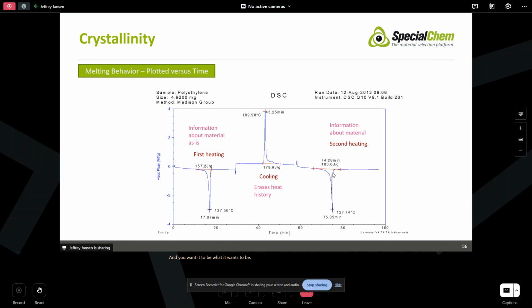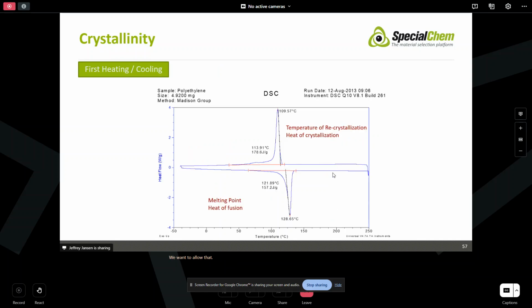And the second heating run now gives us information about the inherent properties of the material, okay, what the material wants to be. You typically, during the molding process, don't want to try and fool the material, you want it to be what it wants to be. It has a structure, it has a molecular weight, again, which are going to lead to structure. You want to allow that to happen. So what we're looking at normally in that heat, cool, heat run is we look at the first heating run and then the cooling run, again, by temperature. And on that first heating run, we get our heat of fusion, we get our melting point. On the cooling run, we get the temperature of recrystallization and we get the heat of recrystallization.